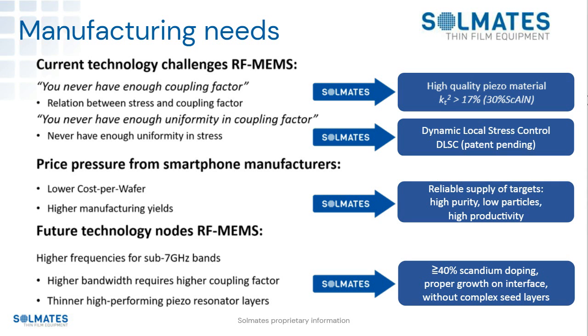So it's coupling factor, right? Scandium doping increases your coupling factor. You never have high enough coupling factor. And of course, coupling factor is also very much device dependent. So if we do our 30% scandium optimization, that's the core of our focus, then we can, from the material properties, derive the theoretical value of a coupling factor of 17. So clearly, it's in the upper range of performance.